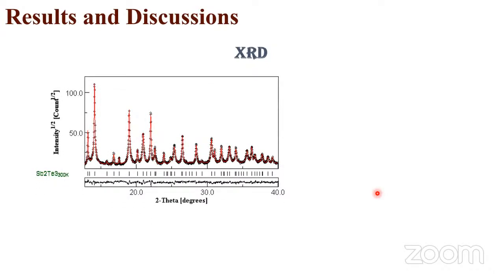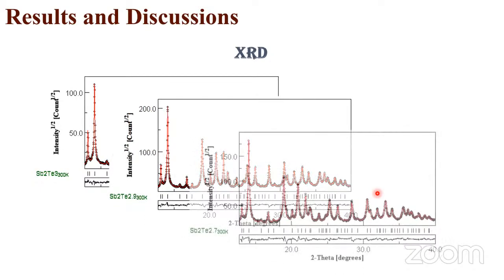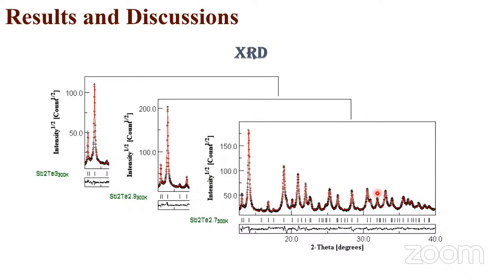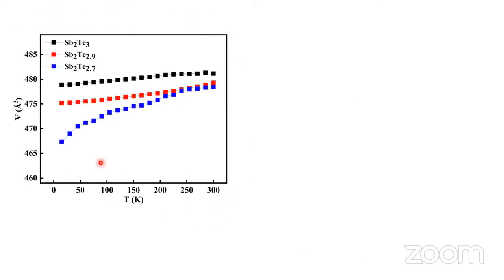At first, temperature-dependent XRD was carried out using the synchrotron facility at KEK Japan. All the XRD data confirm the single-phase nature of the samples. Also, Rietveld refinement was carried out via the software. From the Rietveld refinement, the temperature-dependent lattice parameters and temperature-dependent isotropic thermal factor were obtained. From the temperature-dependent lattice parameter, we can get the volume of the samples. We can see that the volume shrinks with the incorporation of tellurium vacancy,